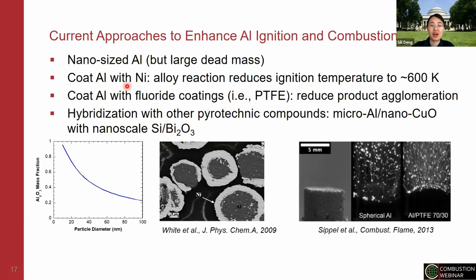Then others have tried to coat aluminum with other reactive metals or coat it with fluoride coatings to remove the oxide layers and also reduce the product agglomeration to enhance the combustion, to shorten the combustion burning time. And some others also try to blend aluminum with other nano-sized reactive materials, etc.